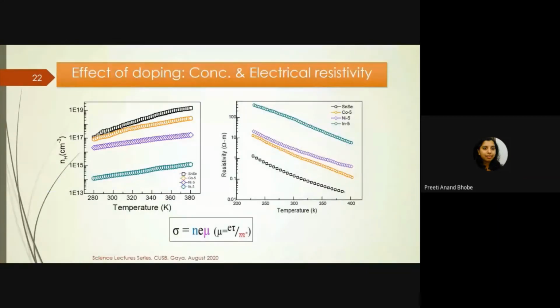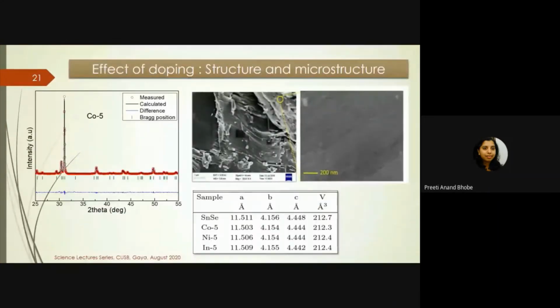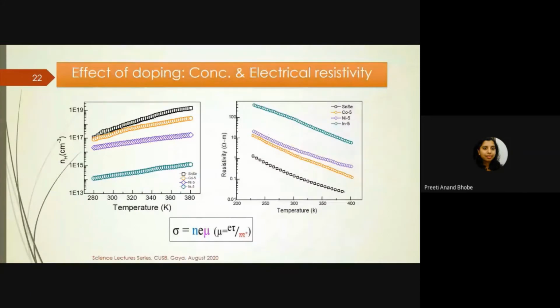Neither do the lattice constants and the volume of the unit cell change. That is also fine. But what is happening is that the carrier concentration changes. What we find is that SnSe has a particular resistivity versus temperature, but by putting in cobalt or nickel or indium, the resistivity increases.